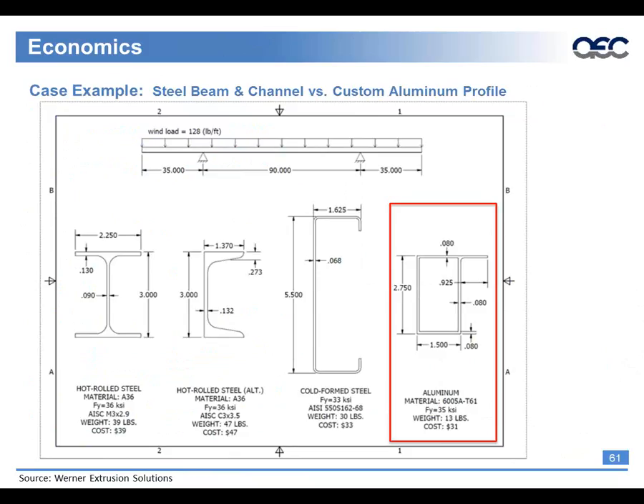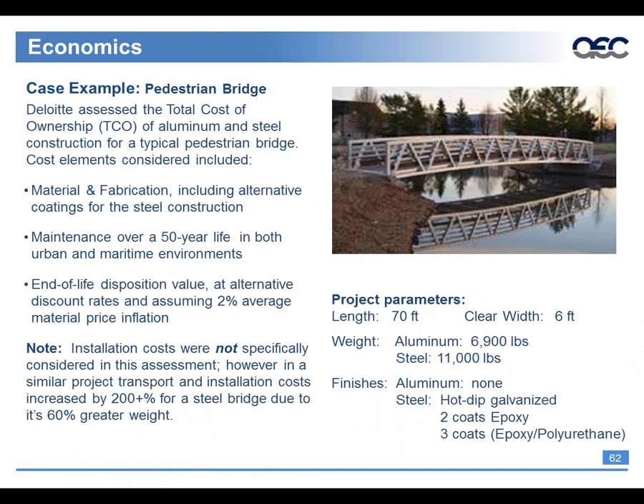You can design in the same amount of deflection resistance with a substantially smaller amount of aluminum. And so even though the aluminum will in fact cost more on a mass basis, taking into account that you've only used a third of the material, you can actually come up with a part that is actually cheaper. And then you get the added attributes of it being more corrosion resistant. So you have a lot less that you may have to put on it in terms of coatings. Next slide.